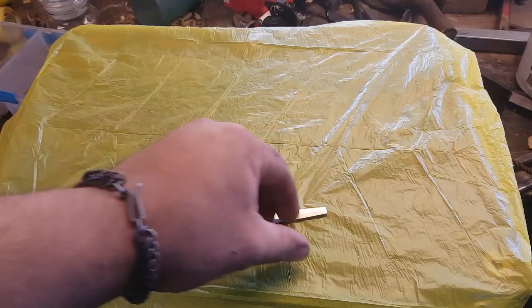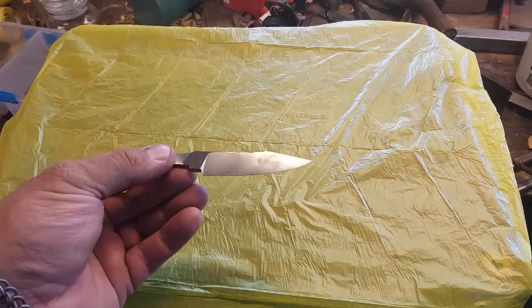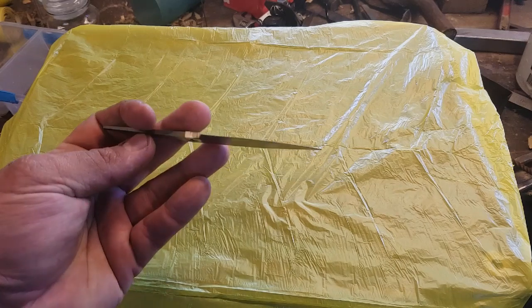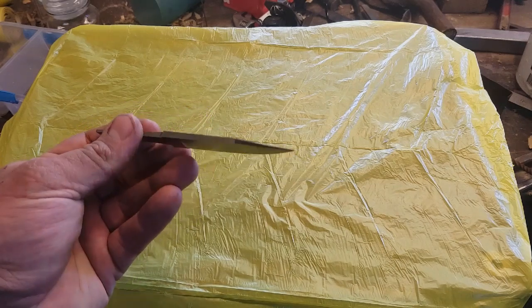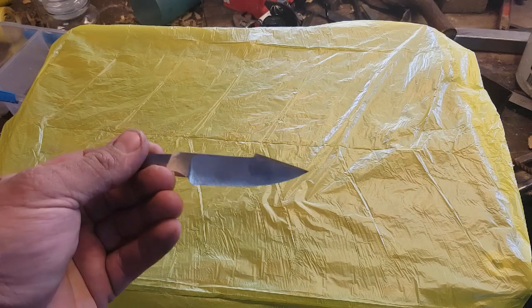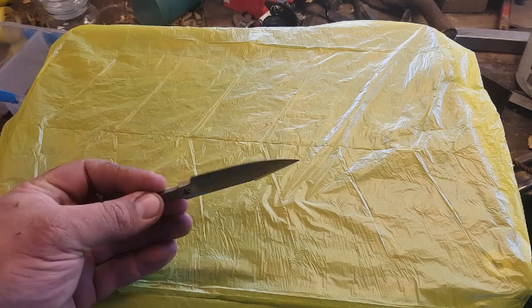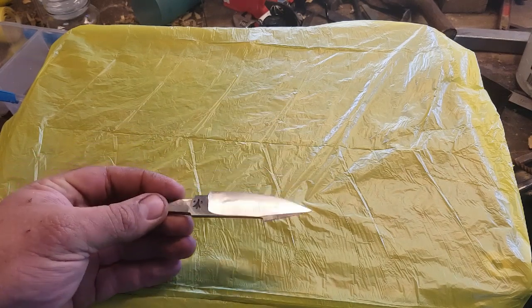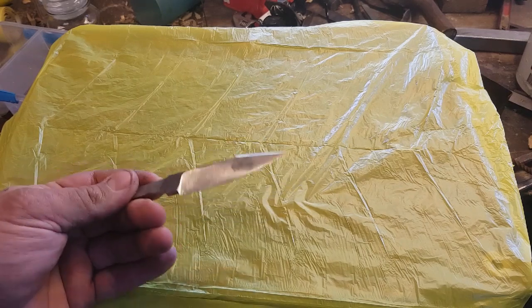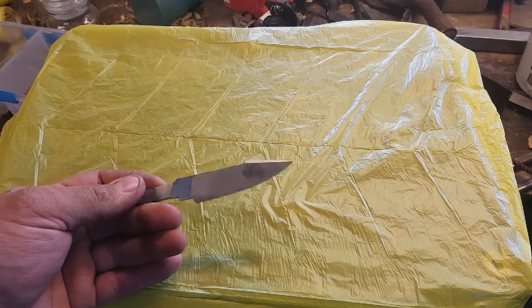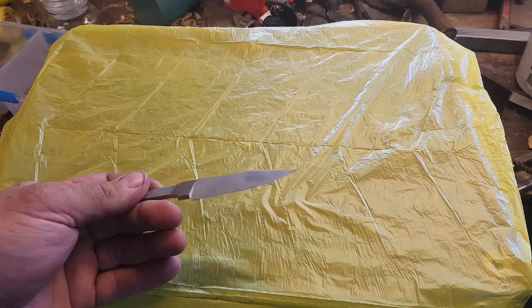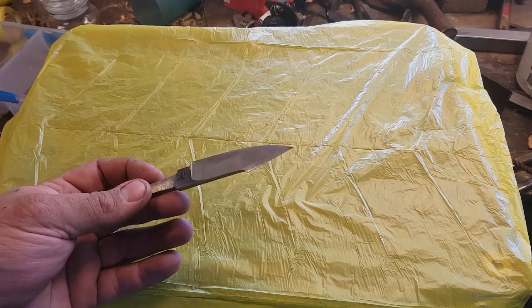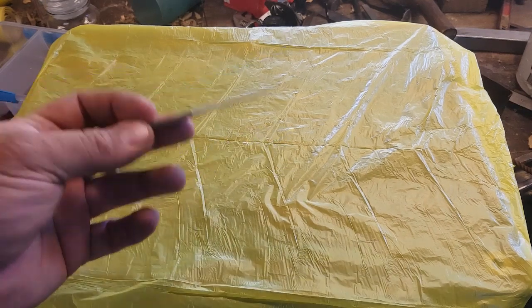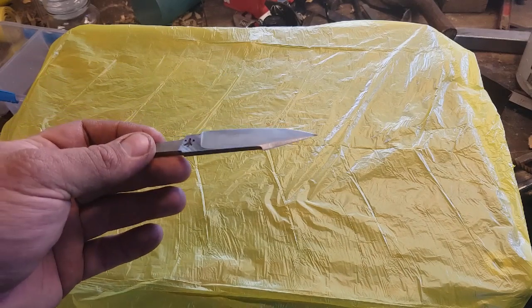Okay, so now that the blade is ground to 120 grit, ready for heat treatment, it's still a little bit thick. It will need post-heat treat grinding, but not very much. The thinner you go, the more active the Hamon will be. Obviously the thinner you go, the more risk you run of cracking it, which is why I go to 120 rather than 40 grit or files or anything like that. But at this stage, it's ready to have the clay applied.